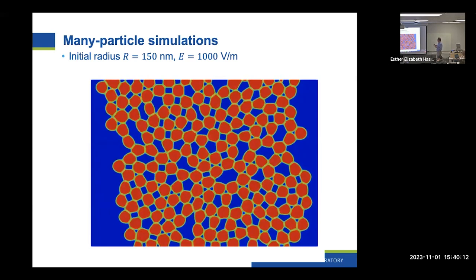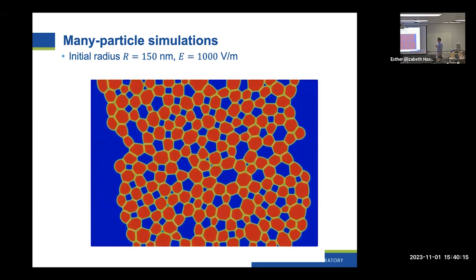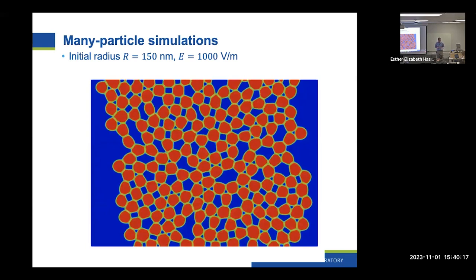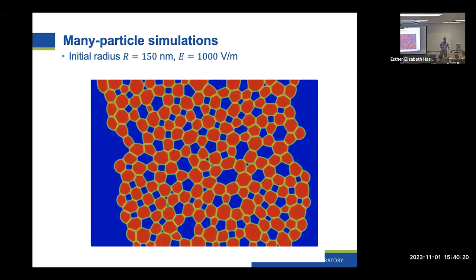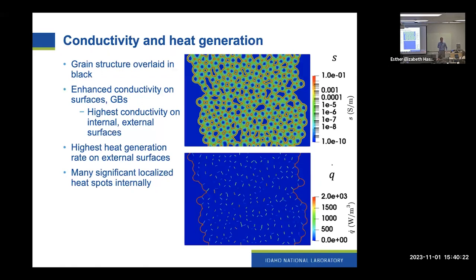as the necks begin to grow, you start to see some grain growth concurrently, as well as some porosity evolution. So we're interested in looking at what the electric field looks like, and what the resulting heat generation looks like. So this shows the grain structure here. And I plotted the electrical conductivity on a log scale here. Otherwise, it's pretty hard to see the grain boundary contributions.